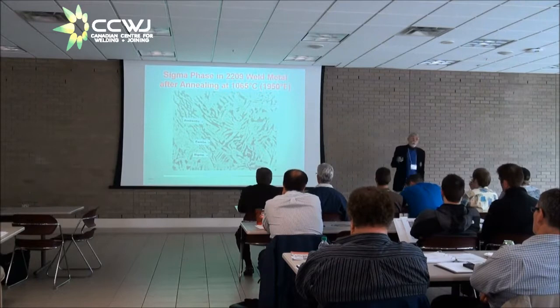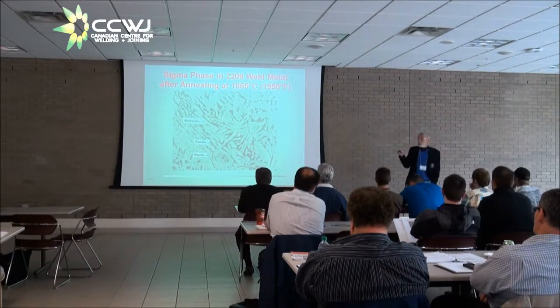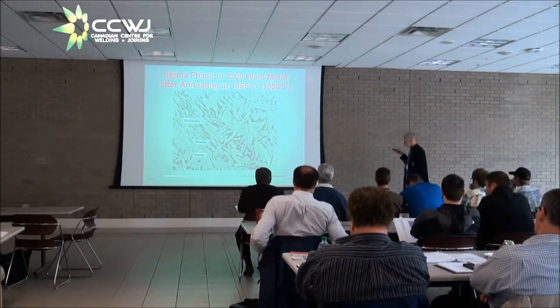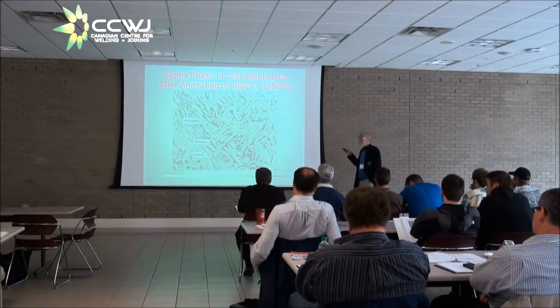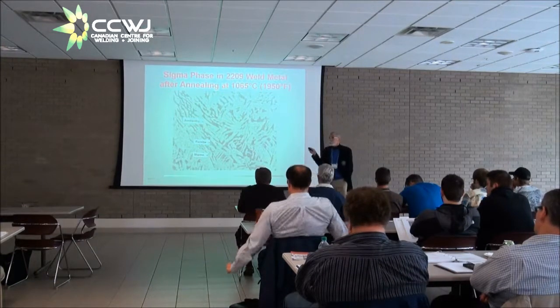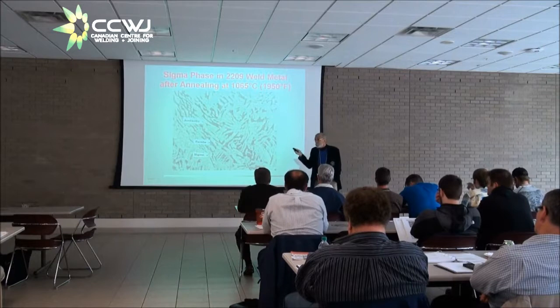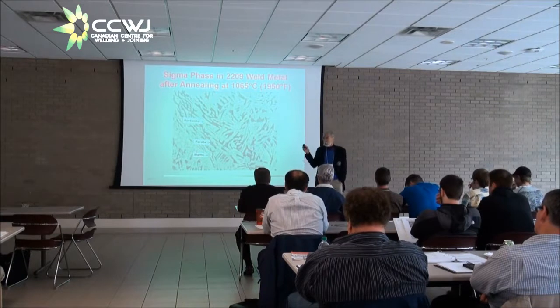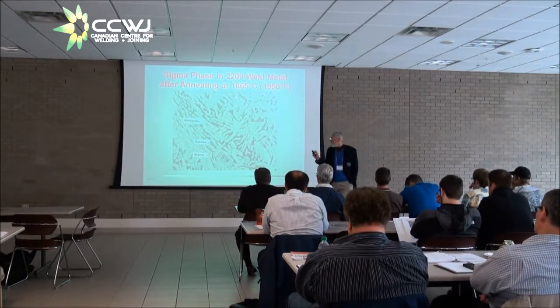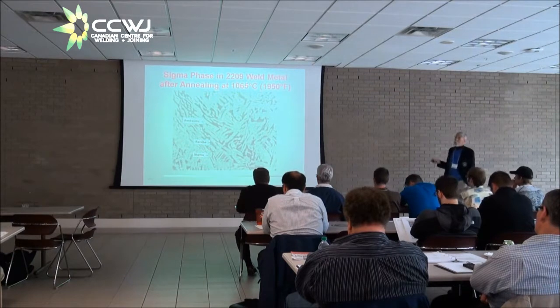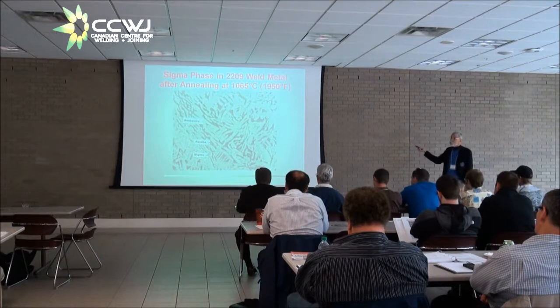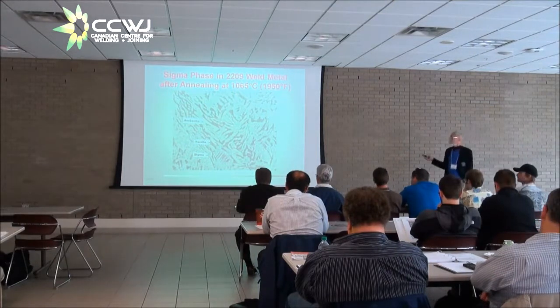So when you say, is the ferrite stable? The question really is, how much ferrite is there? If you got a lot of ferrite, no, it's not stable. If you only got a little bit of ferrite there, yeah, it's stable. Okay, so as a result of that, ASTM revised ASTM A480 to change the annealing temperatures for the 2205 and similar duplexes.